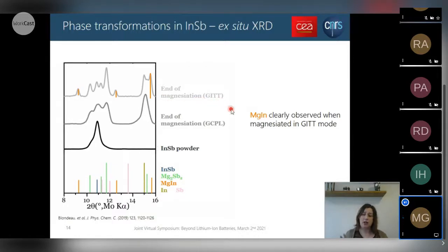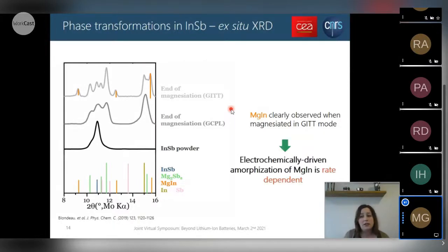So that means that when we are in a classical galvanostatic cycling, the MgIn phase is amorphous. But when the system has time to relax, to reach its equilibrium, the MgIn phase is formed in a crystalline state. So really, this electrochemically driven amorphization of MgIn is kinetically dependent.